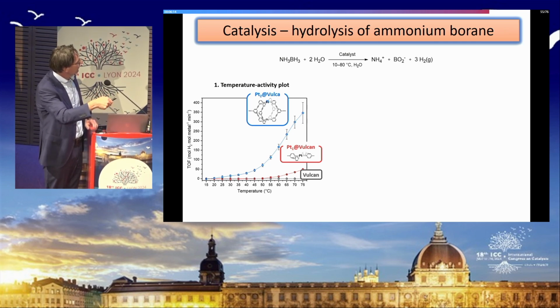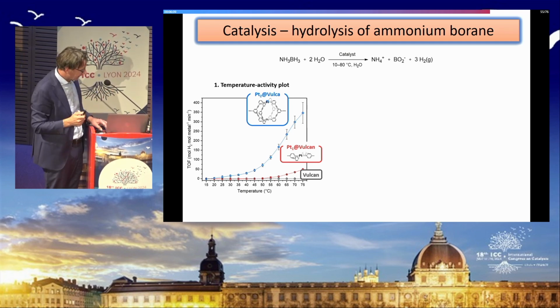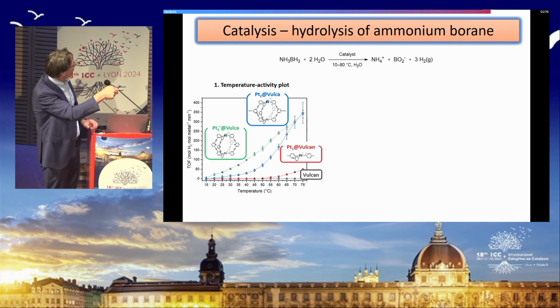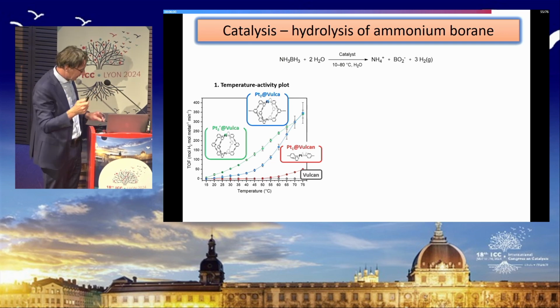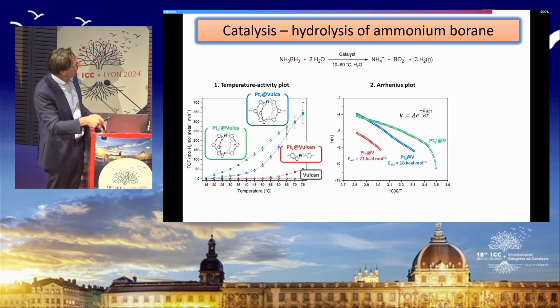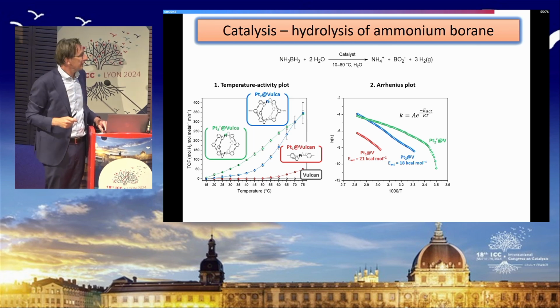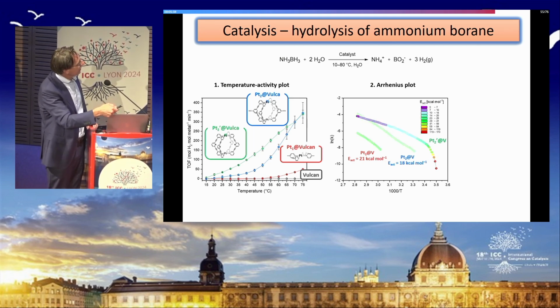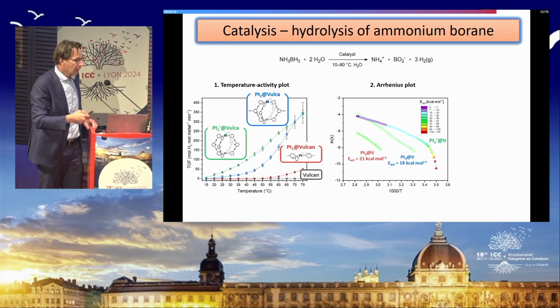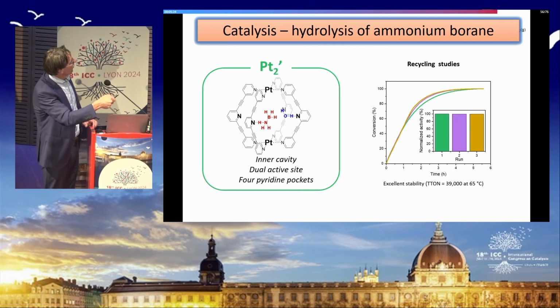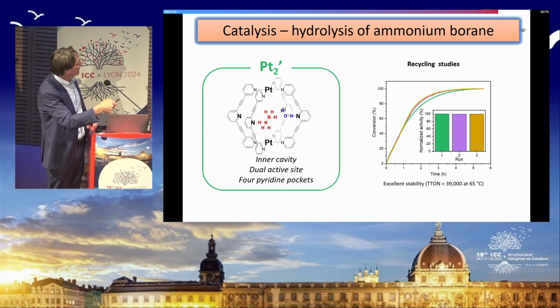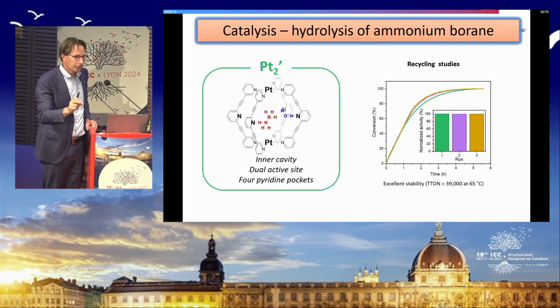Vulcan is not active. The platinum 1 complex is poorly active. And then the cage is quite reactive, quite active in this hydrolysis. And then this cage that also has this amine at the inner side is the most active of all. We can use these data to make Arrhenius plots, and here we have activation energy of the monoplatinum of 21 kilocalories per mole. This cage is a little bit more active, and here we have a curved Arrhenius plot indicating that something is happening as function of temperature. And we can look at the activation energies as function of temperature. And here you see very low activation energies over here, and then it changes gradually. And we think that this has to do with the following. So we probably pre-organize the ammonium borane and the water inside, and this interaction with the pyridine may be a function of temperature, and therefore we see a change in Arrhenius plot.